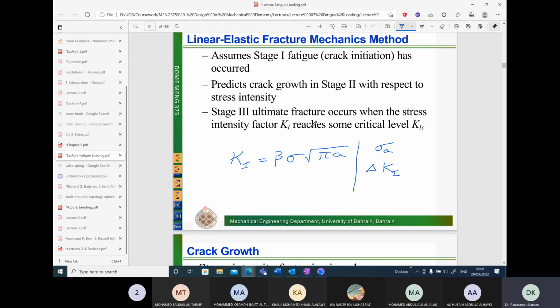We are going to find the same stress intensity factor, but based upon the maximum nominal stress and the minimum nominal stress, we will get two Ki values, and then we are going to take the difference between them. Just like we had the definition of sigma amplitude, in the same way, we are going to calculate delta Ki in this case. Delta Ki will be the difference between the Ki values depending upon the sigma value. Okay, so we assume stage 1 fatigue has occurred in linear elastic fracture mechanics. We assume stage 1 has occurred, and predict crack growth in stage 2 with respect to stress intensity.